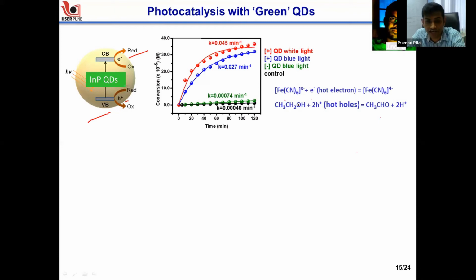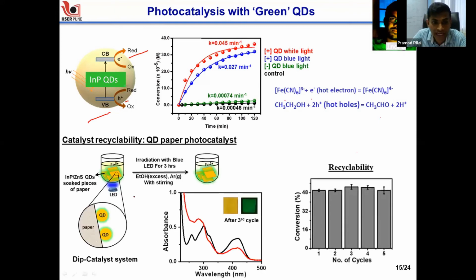In fact, we were able to convert it into a dip catalyst mode where we were able to adsorb these quantum dots on a filter paper, and we were able to recycle this for many cycles. So this data shows that there is no decrease in the catalytic activity even after 5 cycles. So these materials are very compatible, and you can work in a homogeneous condition or a heterogeneous condition.